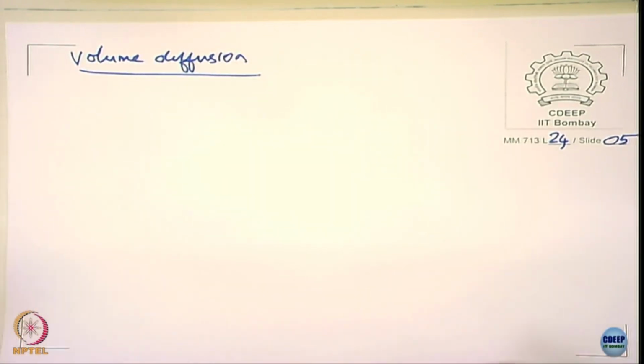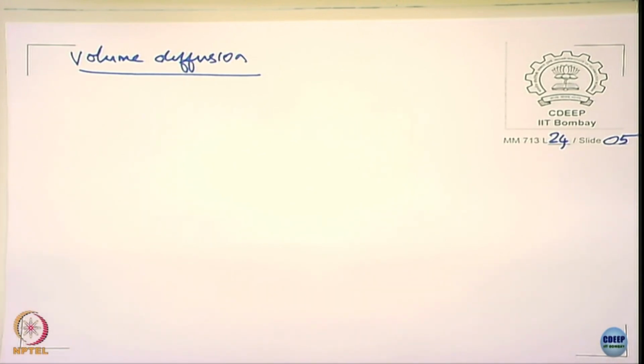So this mechanism does not explain those alloys where the noble metal will not dissolve at all. So there is no question of a redeposition process. So you have the second mechanism which talks about the volume diffusion. Please understand the remaining three mechanisms we talked about, the volume diffusion, surface diffusion, the percolation model, may not invoke the dissolution of the noble element of the alloy. It could say that only the active element dissolves, the noble element does not dissolve in the system, okay.